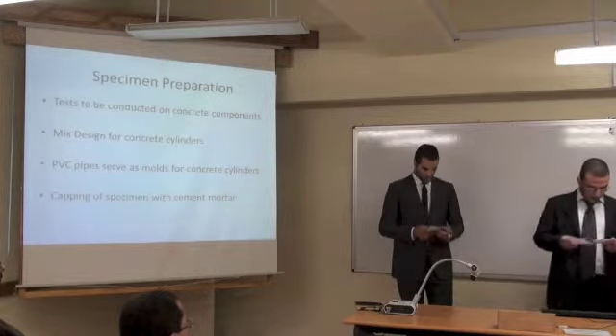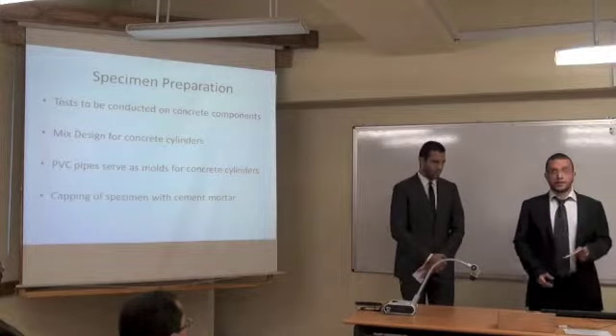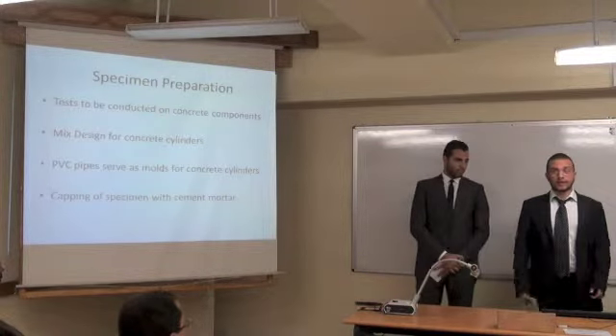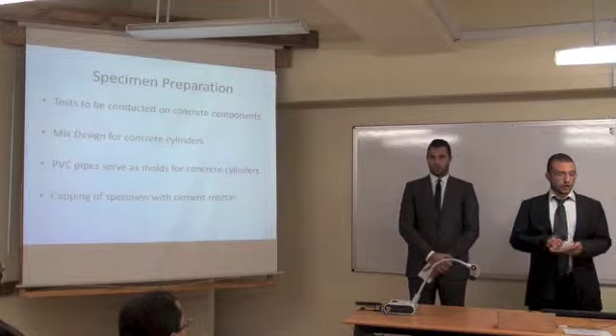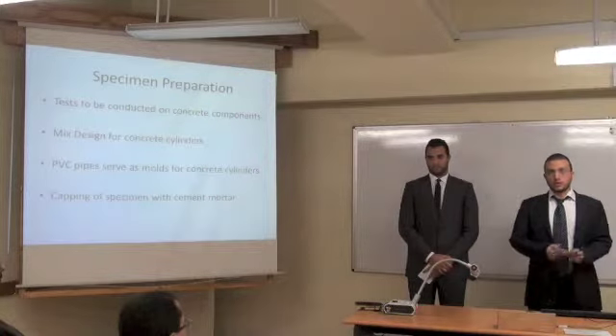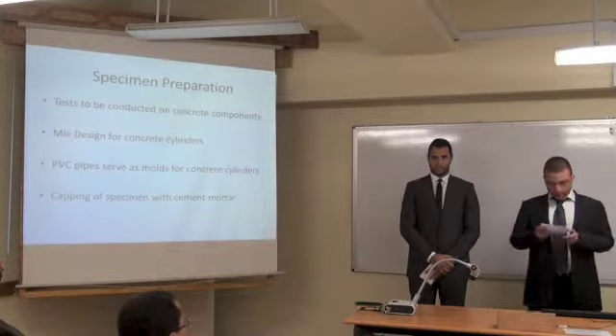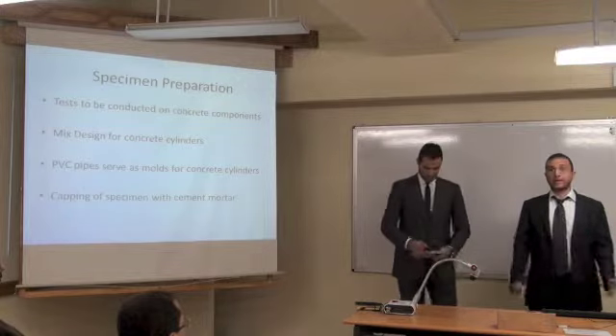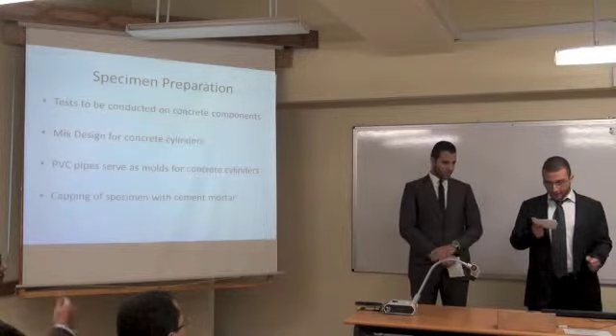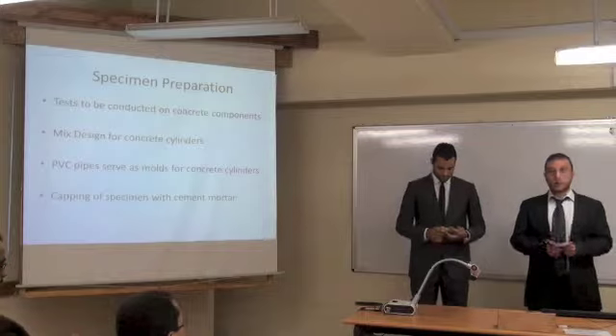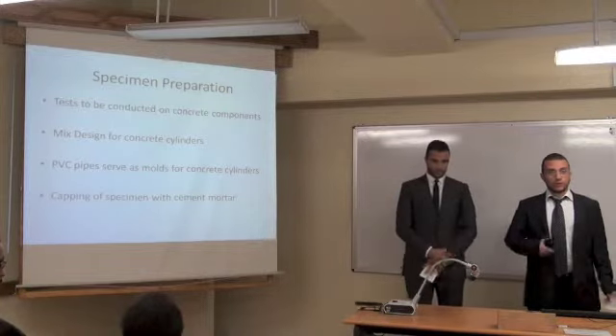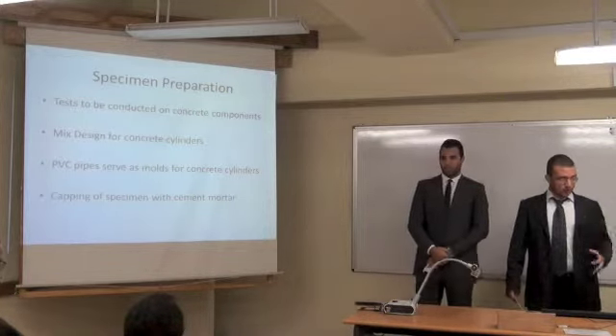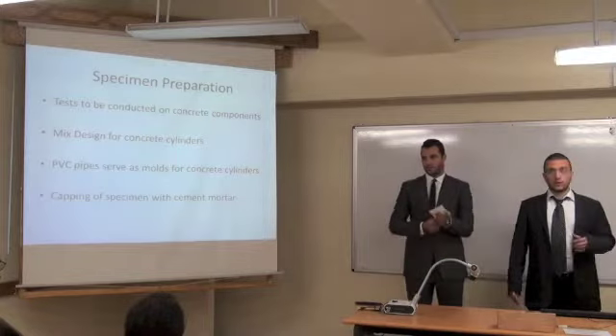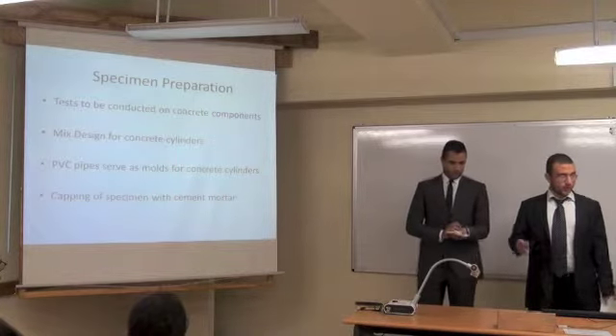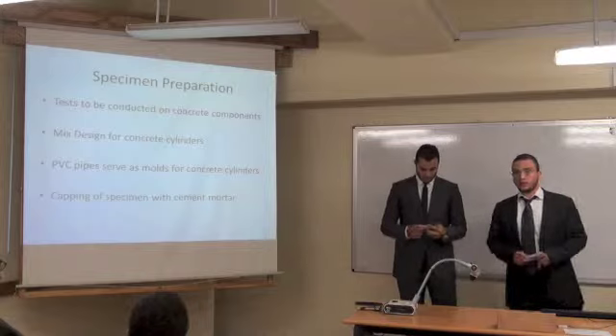Okay, and then for the specimen preparation, first of all we need to conduct tests on the concrete components, the aggregates and the cement, such as the specific gravity, the maximum nominal aggregate size, the rates of absorption, and so on. This information is needed for the mix design, and when we come to do the mix design, we're going to follow the ACI, American Concrete Institute standards.